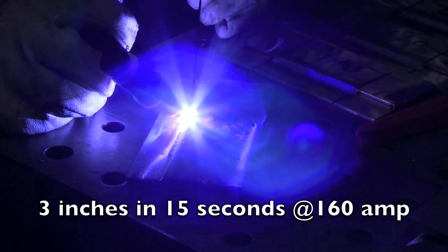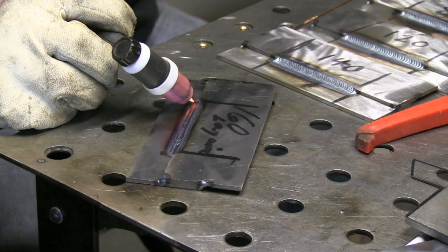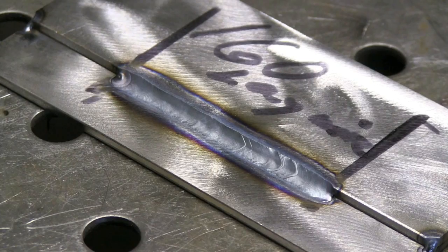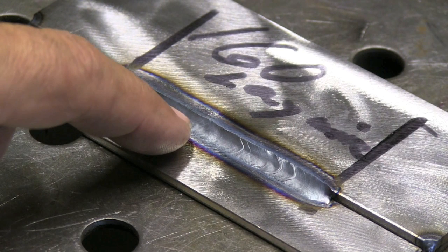What if I use a lay wire technique here and just fly? I don't even dip it. I'm just running over that 1/16th wire just about as quick as I can at 160 amps. You could actually go much hotter and much quicker than this. In fact, this is the way a lot of automated applications are done in industry like tube mills. Welding on seam tubing is done in the feet per minute, not inches per minute range. It just doesn't provide the kind of look that people have come to want as far as the stacked dimes look. But it is a quick way of getting something done.